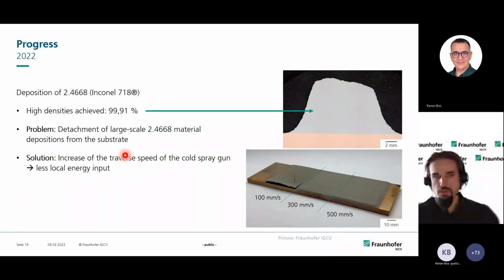detached even during the process and cracked during the process. You can see it here. That's what it looked like all the time. If we were spraying a little bit bigger parts, let's say exceeding a diameter of 50 millimeters, the parts just cracked away from the substrate. Substrate in this case was also copper chrome zircon.